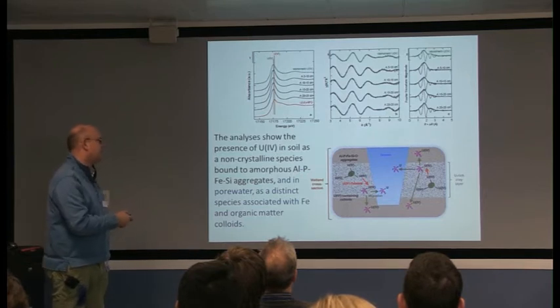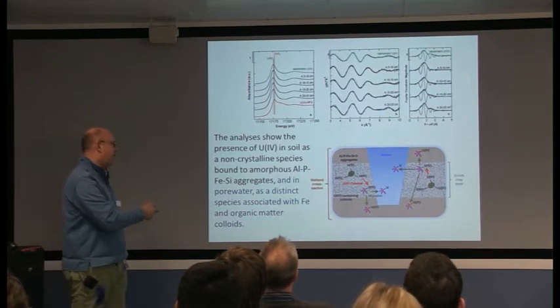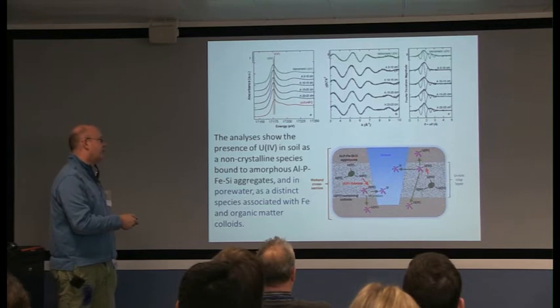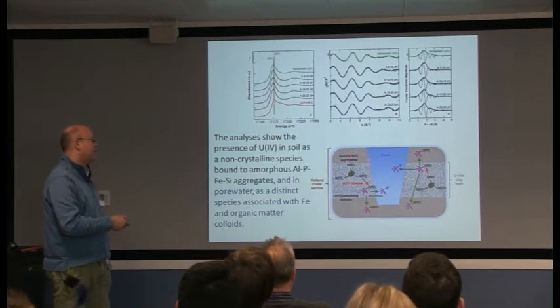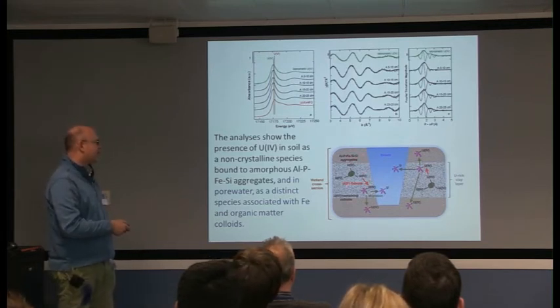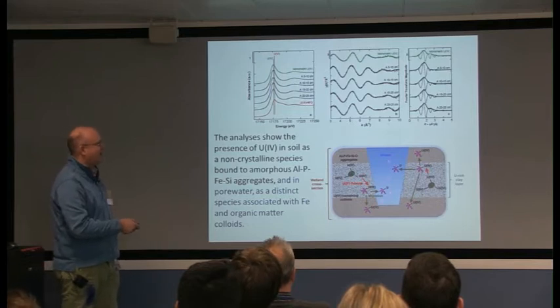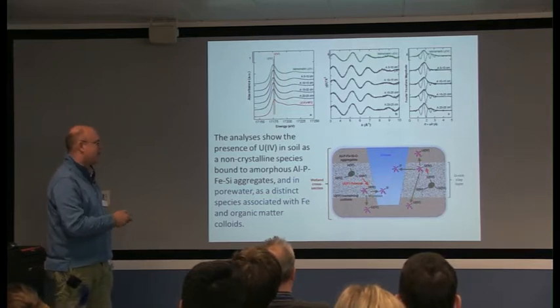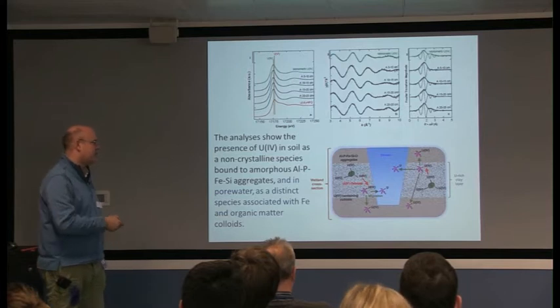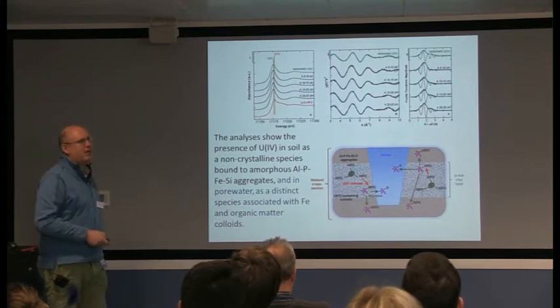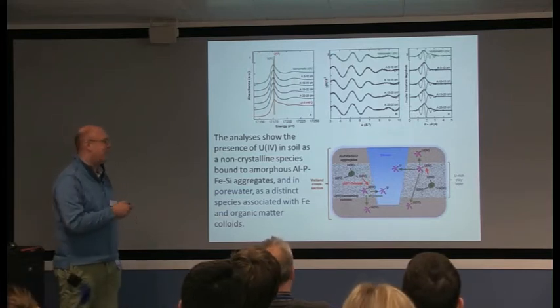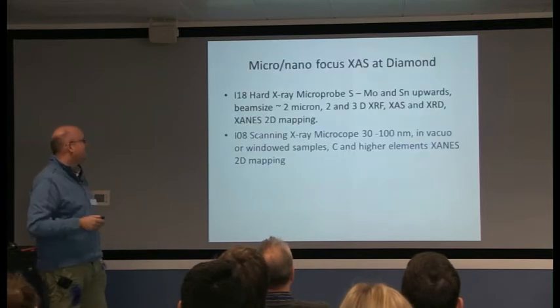It fits with a phosphate, and it's associated, by elemental analysis, with iron, silicon, and oxygen as well. So you've got these colloids that seem to get carried away in the stream and flow downstream. Even though it is uranium-4, you see uranium accumulating quite a long way downstream because of colloid action.